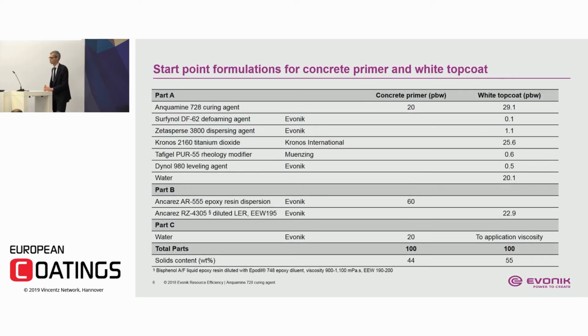I just wanted to show you very basic start formulations. We are clearly not formulators in our product line, so we do a proof of concept, and that's what you see over here. So you see the clear coat primer, which you can also convert into a pigmented primer, and then you basically apply the primer twice to get you 3 to 4 hours on both the primer and the top coat. What we did in the experiments that you saw over here was a clear coat primer and a pigmented top coat. Details displayed over there. There's nothing unusual in this formulation.